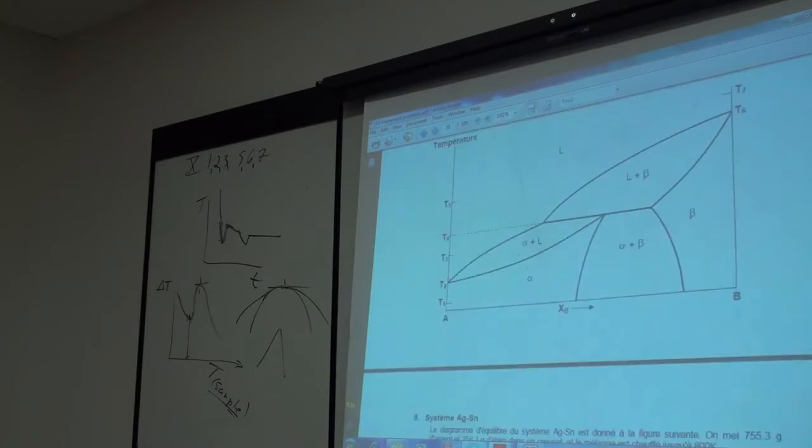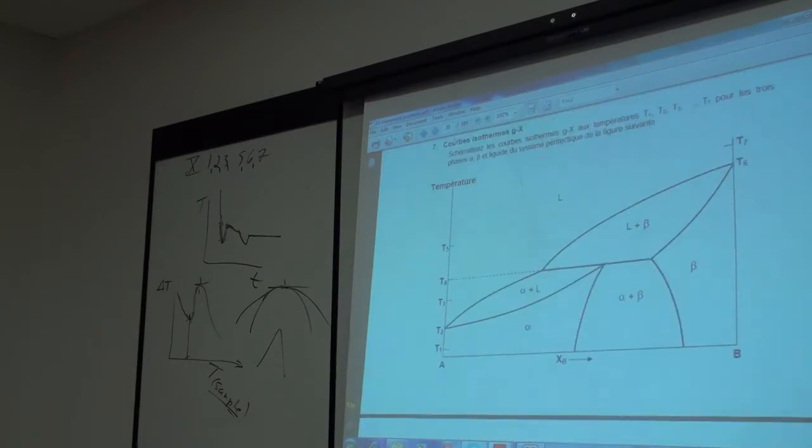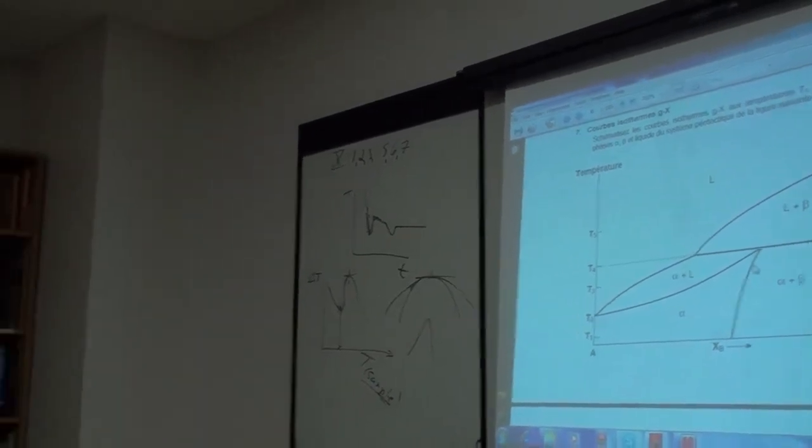And finally, there was a simple peritectic diagram. This proves you can have a peritectic, but there's no compound. So if you have an incongruently melting compound, you get a peritectic, but you can have a peritectic without having an incongruently melting compound. And at several different temperatures, T1, 2, 3, 4, 5, 6, 7, I plotted here the curves, so if you take a look at that.